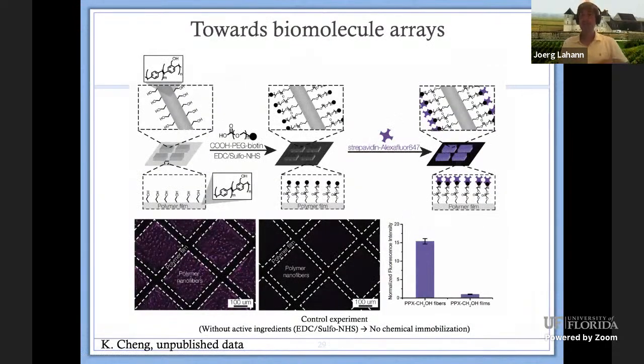Now we can then use functionalized polymers with this. So we can use this as arrays to immobilize biomolecules. The things that we have shown for flat surfaces with respect to immobilization of proteins can be applied to these nanofibers, with the caveat, obviously, that the surface area is largely enhanced. So we get much more binding capacity for the proteins. So this might be interesting for some kind of highly sensitive applications.